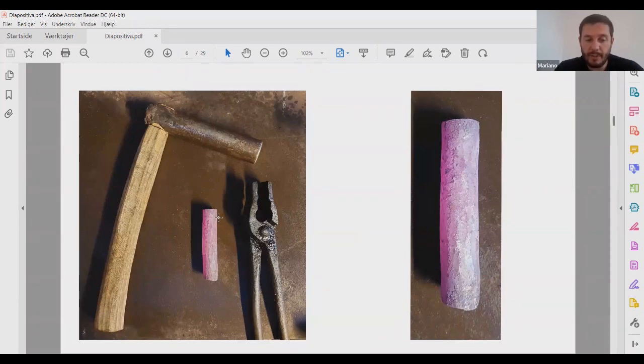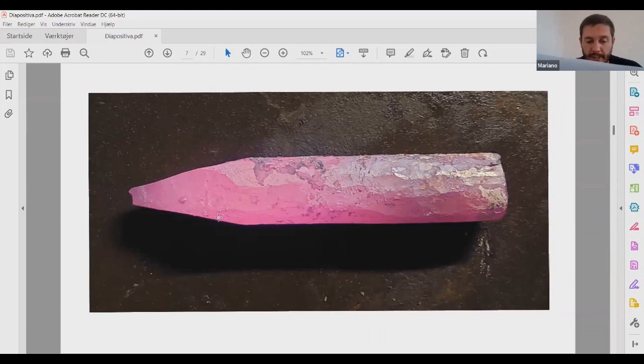To work the material, we are going to use a tong that allows us to hold the bar from the end. The first step will be to heat one end to the forging temperature of the material. We will forge a square point in the end, taking special care not to form a fish mouth, since later it will generate problems in the tip of the knife, and when the material overlaps, it can be difficult to see in future steps.